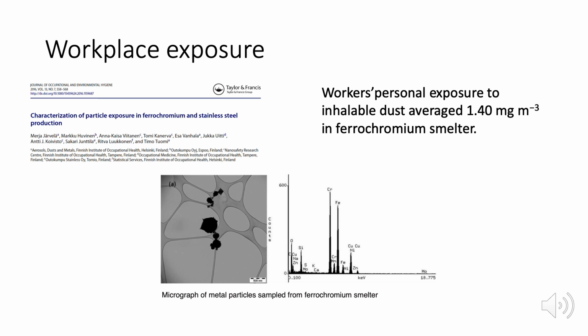This 2016 study from Tornio in Finland describes workers' exposure to fine and ultrafine particles in the production chain of ferrochromium smelting. They concluded that particle number measurements showed a high amount of ultrafine particles, especially in sintering, alloy smelting and melting, and tapping operations. The workers' personal exposure to inhalable dust averaged 1.40 milligrams per meter cube in the ferrochromium smelter. You can see a micrograph of the metal particles sampled from the smelter, and that chromium is contained in those particles.